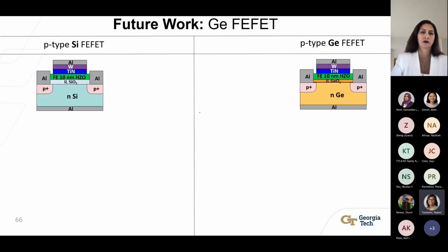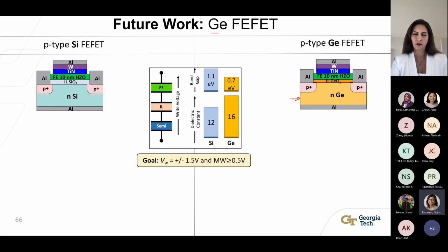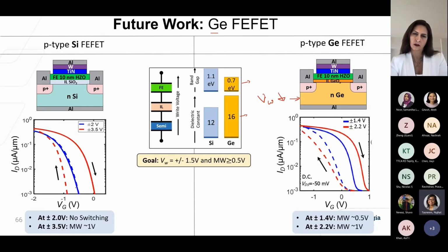So to that end, one of our future projects involved shifting our focus to another parameter of the gate stack of the FeFET, which is the channel, and we changed it to germanium. In case of silicon FeFET, germanium has a distinct advantage because its dielectric constant is higher and it has a lower band gap, which can actually lower the write voltage. Now, in our silicon FeFET, we saw that at 2 volt, there is no switching, and at 3.5 volt, there is around 1 volt of memory window. On the other hand, for our fabricated germanium channel FeFET, we saw that even at 1.4 volt, we see half a volt of memory window, which is very similar to our goal for the embedded application.